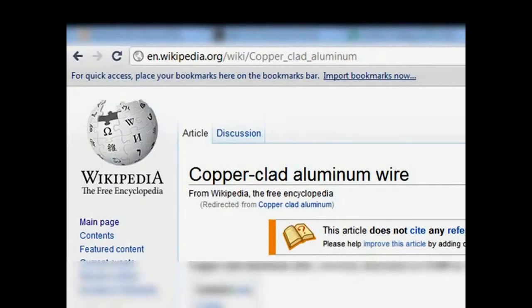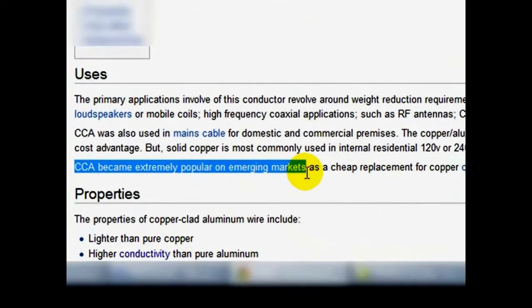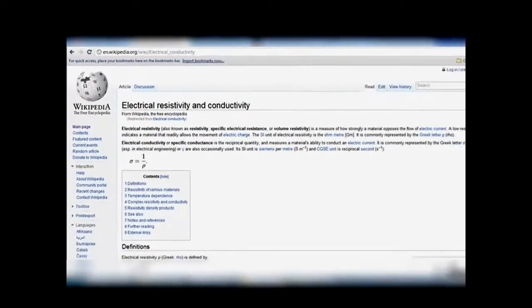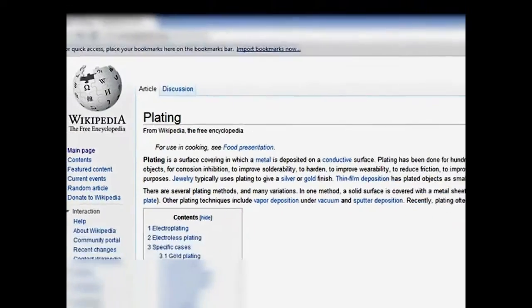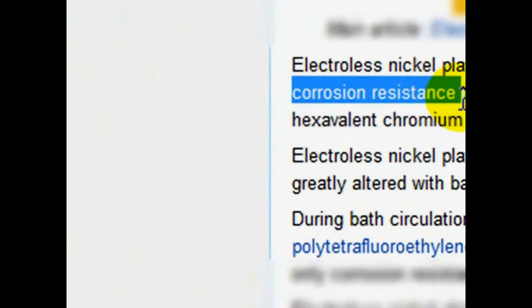Digging a little deeper, Wikipedia describes how CCA, or copper clad aluminum — in other words, aluminum that has been copper plated — has become popular in emerging markets as a cheap alternative to copper. The problem isn't in the price. The problem is that aluminum has nowhere near the ability to transfer power like copper. Because power in the car results from DC voltage at zero hertz in frequency, a zero gauge copper wire transfers almost twice as much power as an equivalent aluminum wire, regardless of the microscopic layer of copper plating. On the other hand, nickel plating over copper, which is what the Ixos cable has, improves corrosion resistance, which is very important in the car environment.